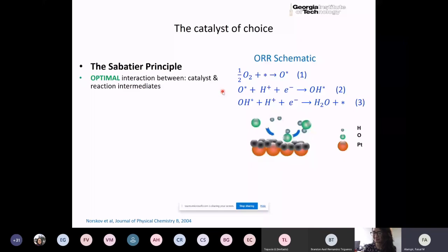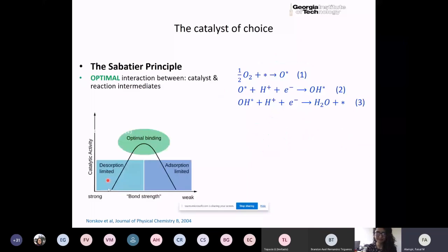That is kind of what the Sabatier principle is about. So there's an optimal, if you look at, for example, catalytic activity, and you look at whether or not a material is bonding to, when you have a catalysis reaction, you have to have reactants that bond to the surface of your catalyst. And what you want for that catalyst is you want the reactants to bond, but not bond too strongly. Right, so you want to make sure that there's sufficient bonding so that you can actually promote the reaction. But if it bonds too strongly, then it slows down the reaction. So there is an optimal bonding strength.